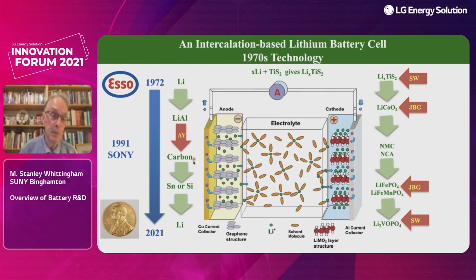So the potential to replace them by silicon, we've shown that tin compounds work very well, in fact better than silicon, but obviously there's weight and volume issues. But the ideal endpoint is to go full circle back to lithium again. On the cathode side, we started out with a layered compound, TiS2. It worked very well, and I'll show you why in a minute.